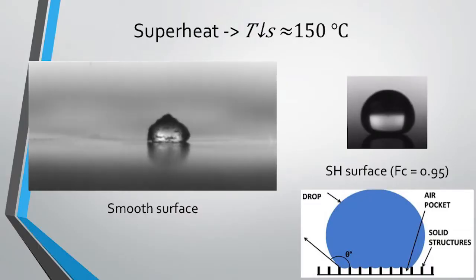But what if we heat it up even more, right? We'll go to 150 degrees C. Maybe this is going to get a little bit better. On the smooth surface, it actually gets more exciting, right? So now it's boiling so hard, it literally removes itself from the surface. So there it goes. And then it's actually really cool. You can see as it removes itself from the surface, as soon as it's not in contact with the surface, it immediately stops that violent boiling. So it's the same idea. There's that air gap where heat is not transferred through there.